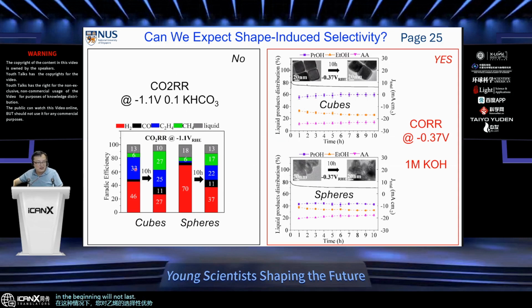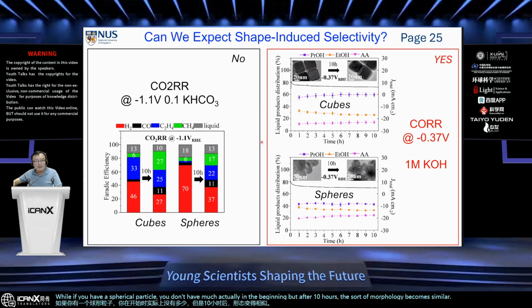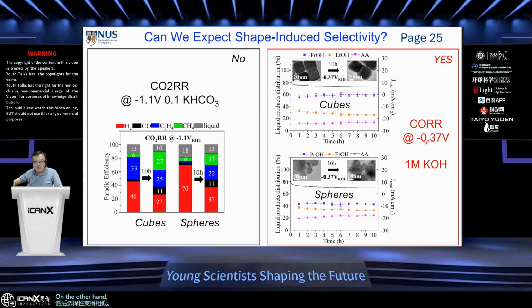This is exactly what we found, right? After 10 hours, the acetylene selectivity changes from 33% to 25%. While if you have a spherical particle, you don't have much acetylene in the beginning, but after 10 hours, the morphology becomes similar, then the selectivity becomes similar. On the other hand, if you can work with more positive potentials, more positive than negative 0.4 volts, you can maintain the morphology. You can actually maintain the morphology-induced selectivity.